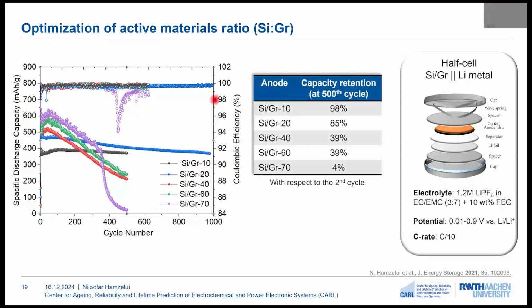If we compare the capacity retention of these electrodes after 500 cycles, this value is 98% for the electrode with 10 weight% silicon, and it reduces to 4% for the electrode with 70% silicon. And among these electrodes, the electrode with 20 weight% silicon showed a more stable performance, and after almost 900 cycles, it shows a capacity retention above 80%.